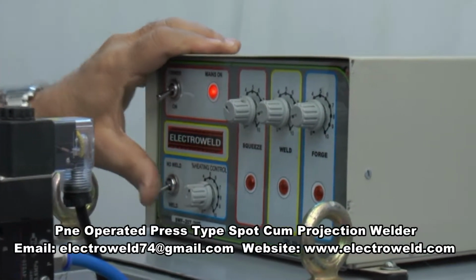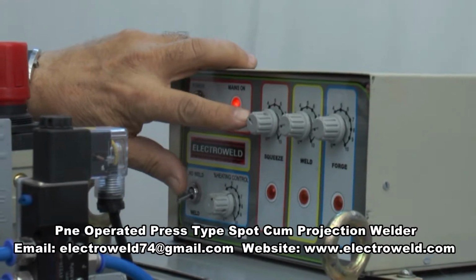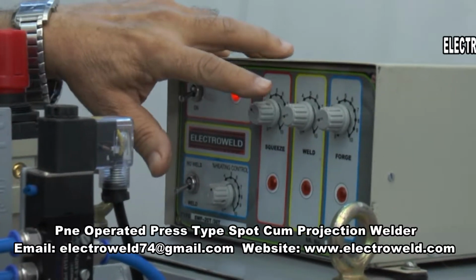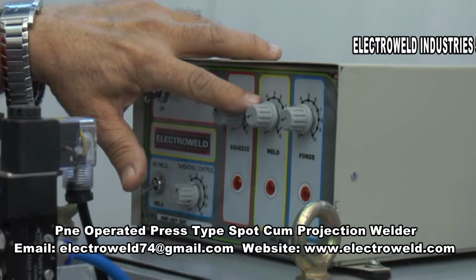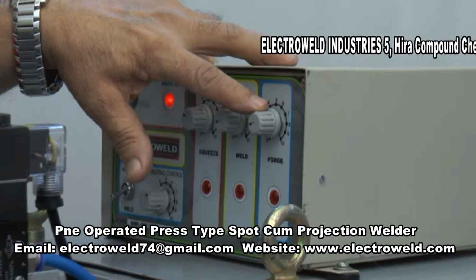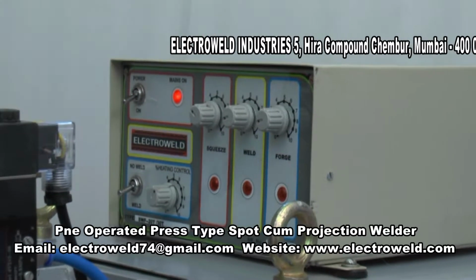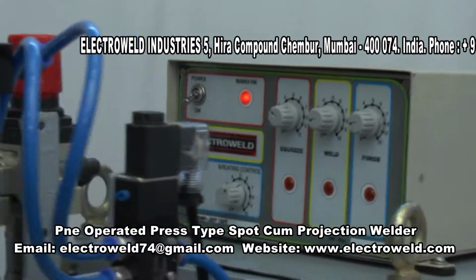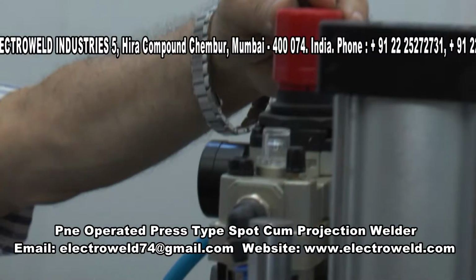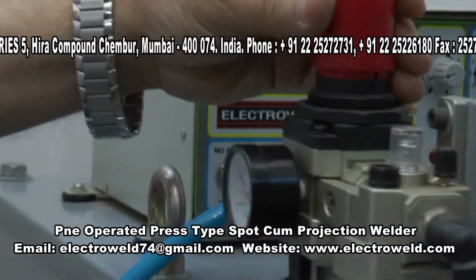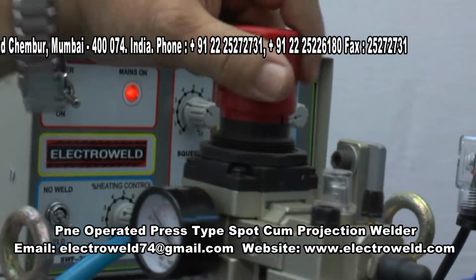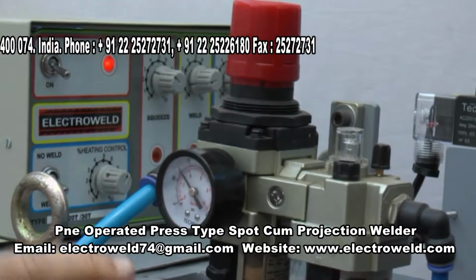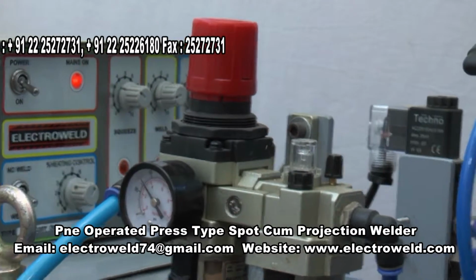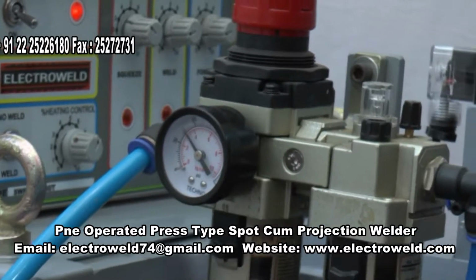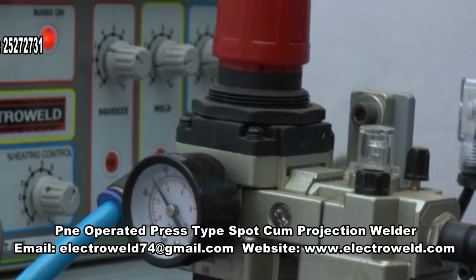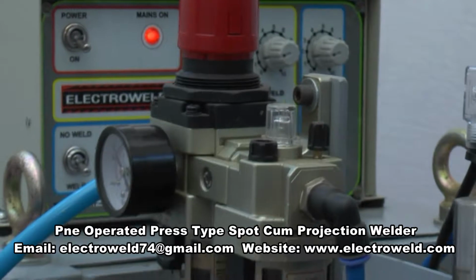tap current. Squeeze time say about 30 cycles, the weld time about 10 cycles, and the forge time about 10 cycles. And the pressure over here you can adjust for 6 mm plus 6 mm rods to say about 30 psi. Like this, you can read the pressure 30 psi. Now the 3 parameters like current, pressure and the weld time are adjusted.